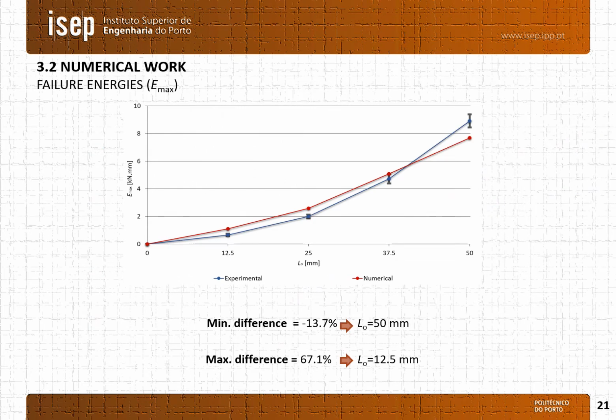Now presenting the experimental and numerical comparison of the failure energy evolution as a function of the overlap length increase, it is possible to observe a satisfactory agreement. The minimum difference is minus 13.7% for an overlap length of 50 mm and the maximum difference observed is 67.1% for an overlap length of 12.5 mm.